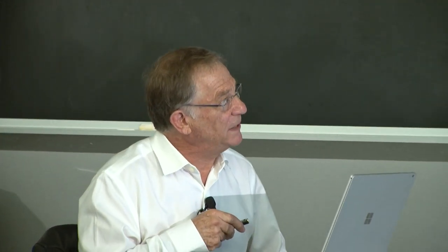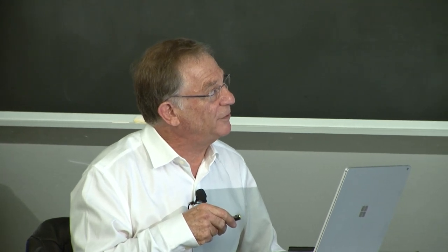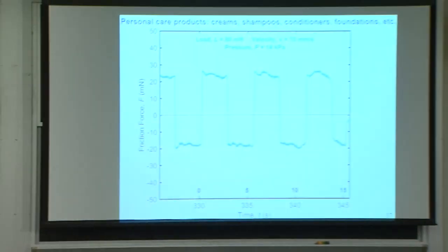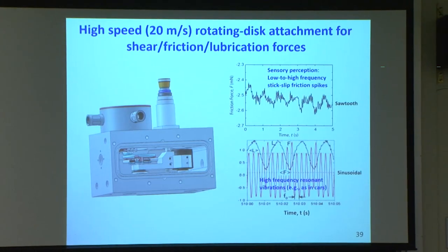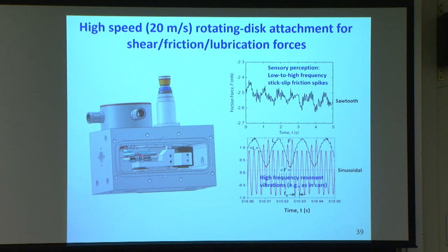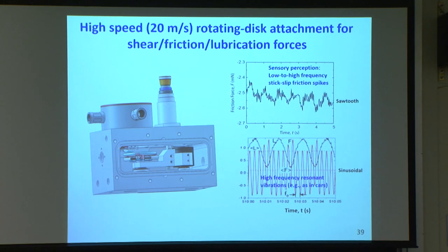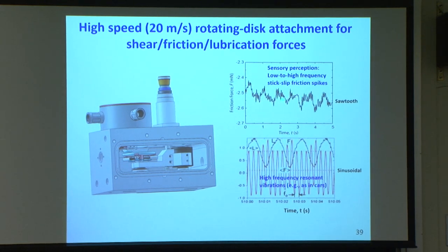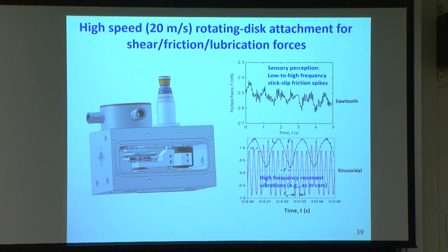Okay. So here's some typical friction traces that most people might just measure and say, oh, here's the average friction and so on. But actually, it turns out that there's a lot of information, and we developed something that allows us to measure over many, many orders of magnitude in velocity because, you know, you can feel things slowly or fast. And there's a lot of interesting features. So here, for example, is a friction trace, and you can see there's two types of stick slip superimposed, one at one frequency and one at another frequency.